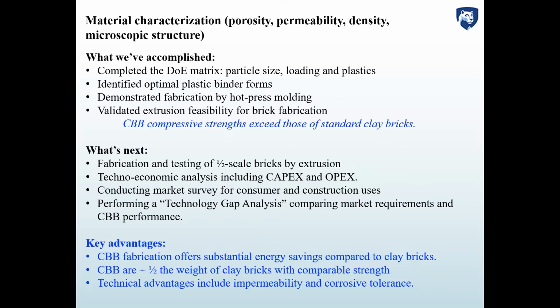The key advantages, again, of our bricks are that CBB fabrication offers substantial energy savings compared to clay bricks, half a day to a day and a half of firing compared to 30 minutes at a reduced temperature. The CBBs are roughly half the weight of clay bricks and of comparable strength.